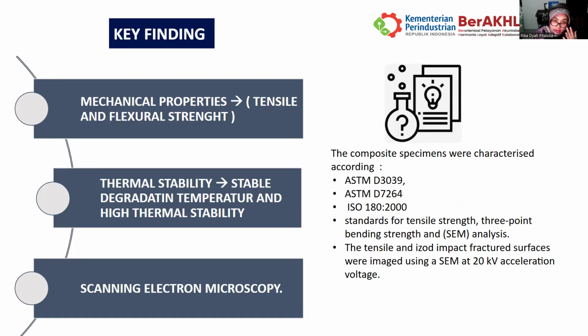To add more on this key finding, the composite specimens were characterized in accordance with ASTM D3039, ASTM D7264, and ISO 180:2000. All of them cover the standards for tensile strength, three-point bending strength, and impact strength. The tensile and Izod impact fracture surfaces were imaged using SEM at 20 kilovolts acceleration voltage.